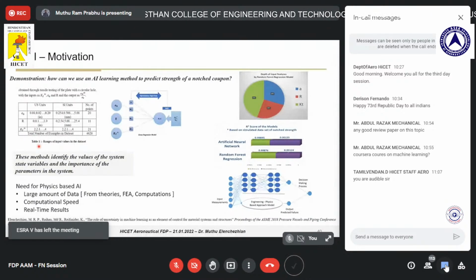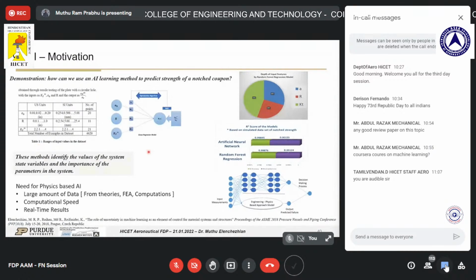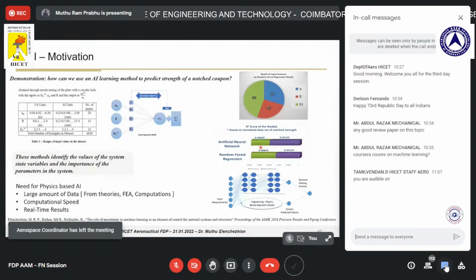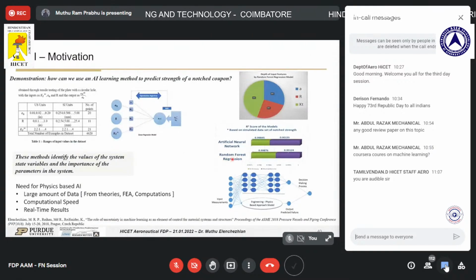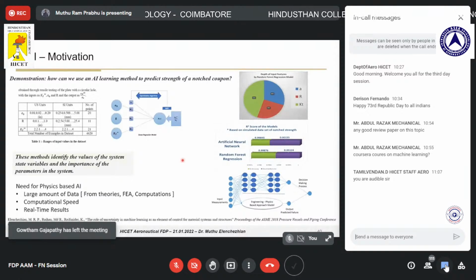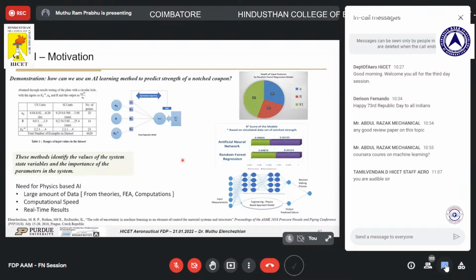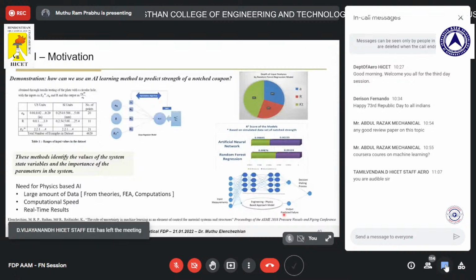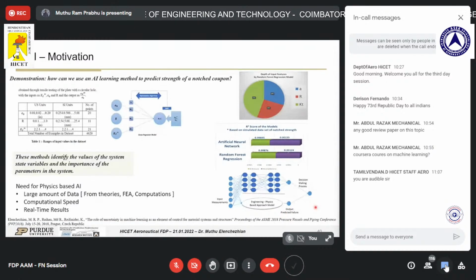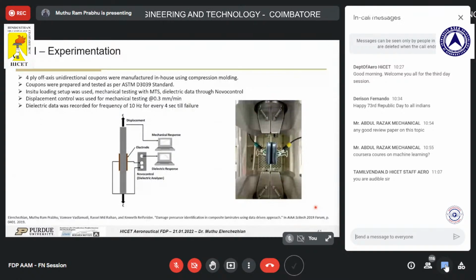And since this data set is completely developed from a physics-based equation, the accuracy of the models, the R-square score, is very high. It's more than 99.8% in both cases. And with the random forest regression, you can also identify what features contributed to the output prediction of the model. The main goal of this work is that apart from experimental data, instead of just using the data to develop the actual output model, if we use some known physics in between, when there's a large amount of data involved, you will be able to develop a complete hybrid model. And this hybrid model will be able to develop the result more accurately and lead to the final decision-making process.